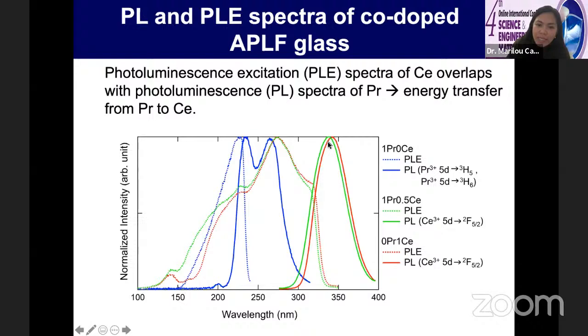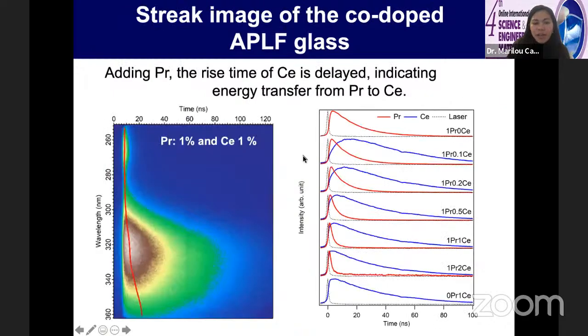Yeah, so here we can see the emission from praseodymium, but we can see that the excitation spectrum of cerium overlaps with the emission of praseodymium. So this tells us that there would be some energy transfer from praseodymium to cerium ions. So we investigate the energy transfer further.